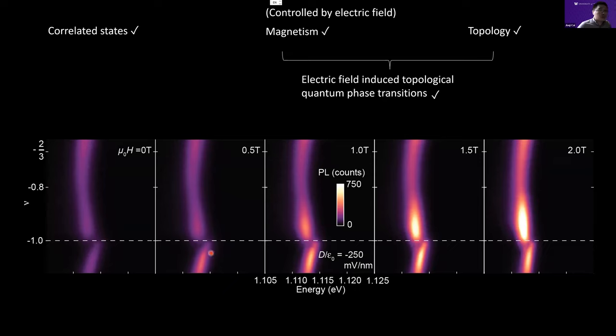So there is no dispersion at all at this time for nu equals minus one, and there are not even the fractional Chern states. So this tells us the electric field can actually introduce a topological quantum phase transition from those topological correlated states to topologically trivial correlated states for nu equals minus one. And it has basically killed these fractional correlated states.